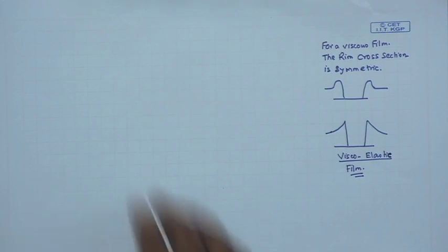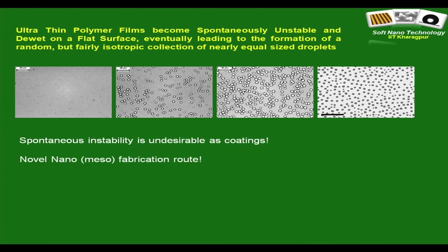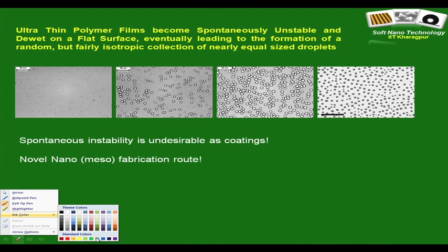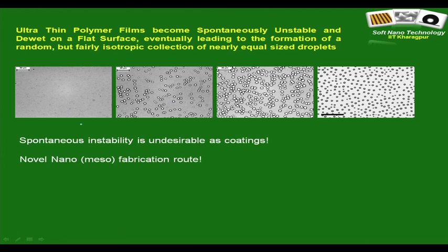But what we will focus on in this lecture is something different. We are now all familiar with this particular picture, which is essentially the key evolution sequence of a polymer film. So you have a flat film, and what I had hinted is that one fascinating aspect is you only spin coat a flat film and do nothing. These films behave like solid at room temperature, because their glass transition temperature is above room temperature. If it is a polystyrene or a PMMA film, the Tg is close to 100 degrees centigrade. So at room temperature, irrespective of the wettability of the substrate, the sign of the effective interface potential, you are not going to see any dynamics.